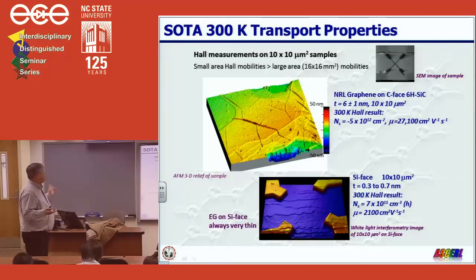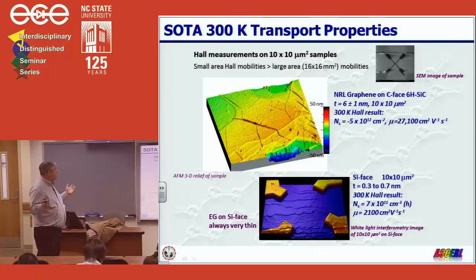Okay, transport properties. Naturally, since we're in the semiconductor business, we want to do Hall measurements. So we form little Hall crosses, and as I mentioned before, it's just standard lithography. And you can see an image of one of the crosses. Here's an SEM image in the upper right. And the middle portion shows one of our best samples grown on the carbon face.